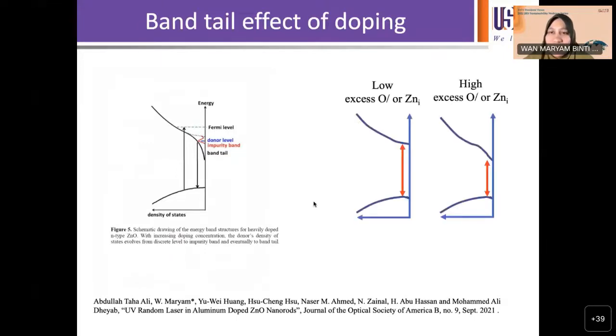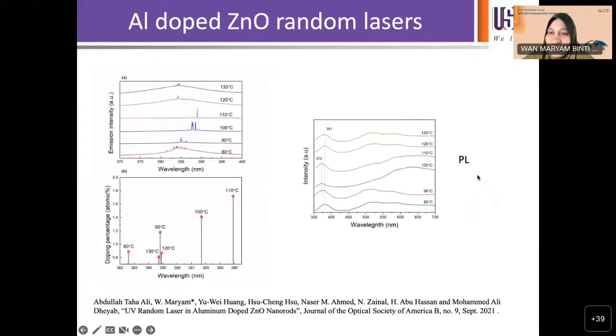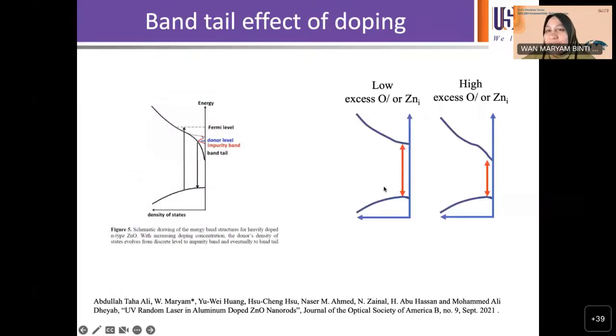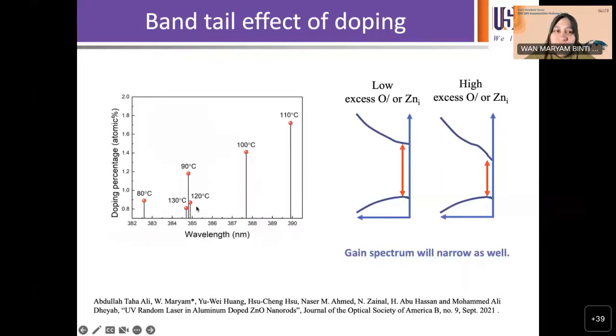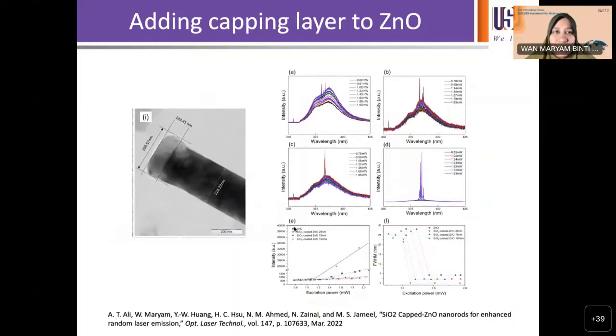And this gives rise to changes in the energy, so when you get the photoluminescence, you will see the luminescence peak coming here instead of here. Okay, this is due to excess oxygen or excess zinc. In our case, it's excess oxygen. So we see this in our sample, which gives rise to this change, right? Basically, it shows the possibility of tuning the wavelength of a random laser with the presence of doping. So this is what we are trying to prove. Okay. Then we started to introduce a capping layer.